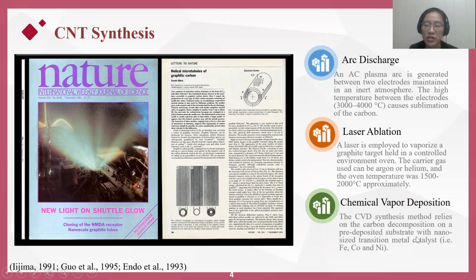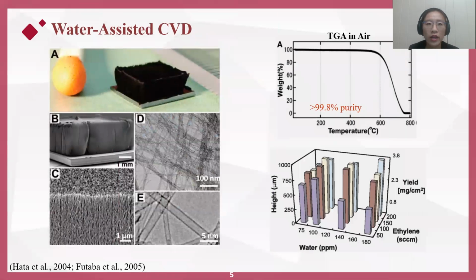The conventional CVD process, on the other hand, requires remarkably lower synthesis temperatures for the CNTs to grow on a pre-deposited substrate. In the early 2000s, a Japanese group took an innovative approach to introduce a controlled amount of water vapor into the CVD process in synthesizing CNT, yielding single-wall CNTs as shown in this TEM image with over 99.8% purity. They believed that the water vapor served as a weak oxidizer and selectively removed the amorphous carbon without actually damaging the CNT network. With a prolonged catalyst lifetime, this technique is anticipated to provide a simplified approach for achieving high purity CNT synthesis more efficiently.